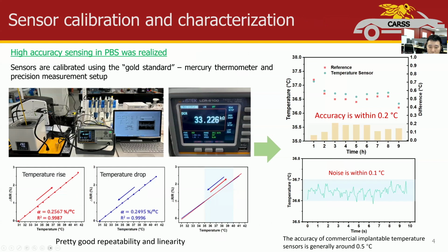Our sensors were calibrated using the gold standard, which is mercury thermometer in a precision measurement setup. The data shows our sensors have pretty good repeatability and linearity. In addition, the accuracy is within 0.2 Celsius and the resolution is 0.1 Celsius. So high accuracy temperature sensing was already realized.